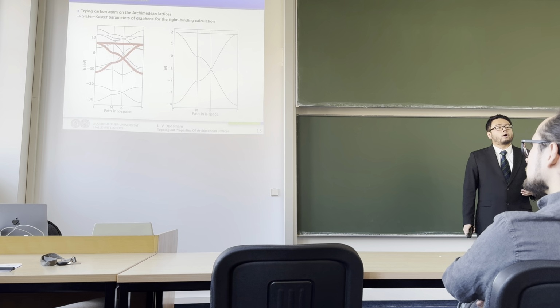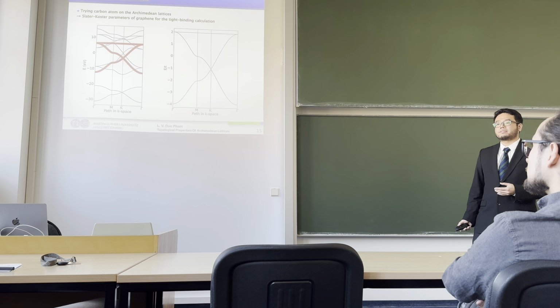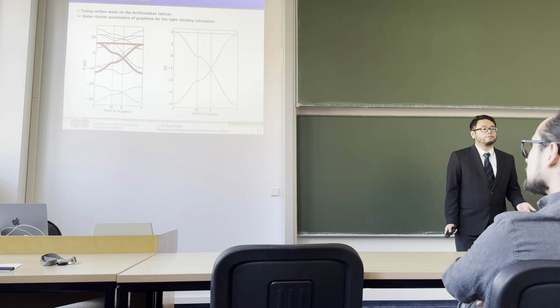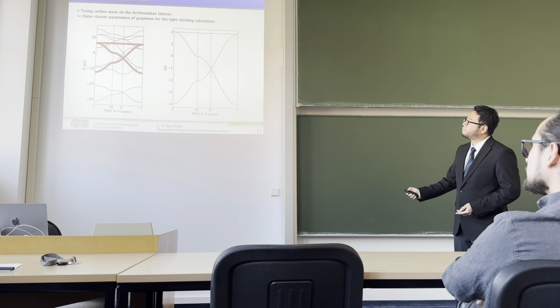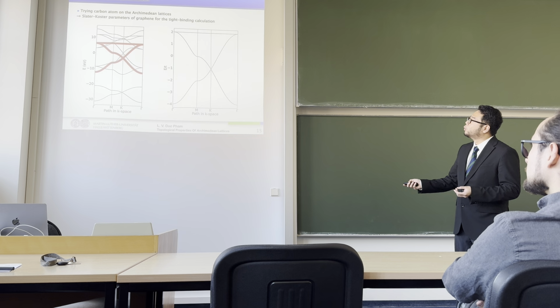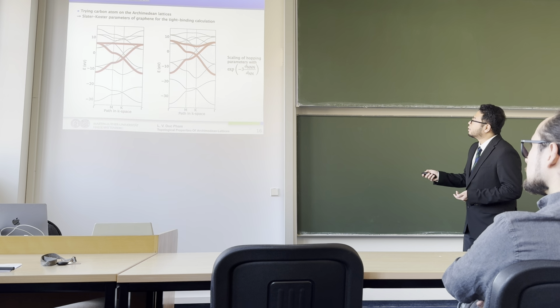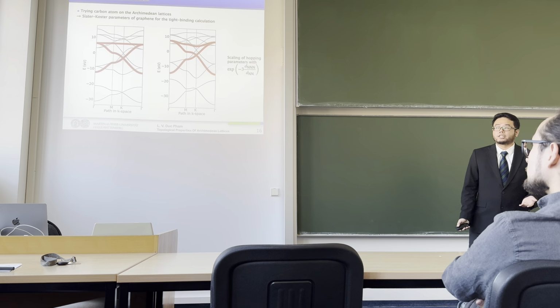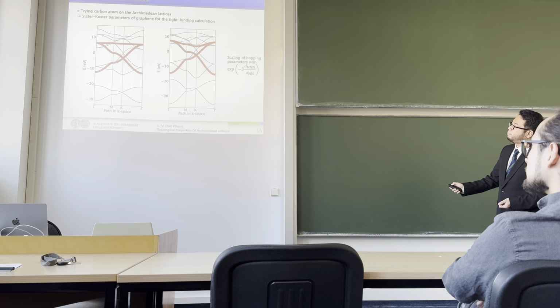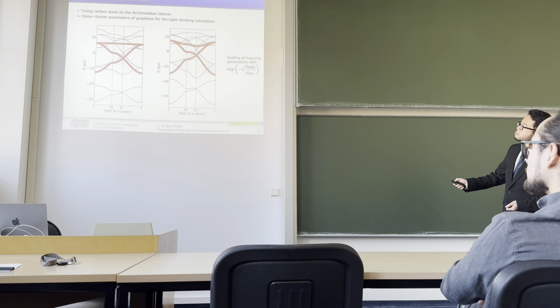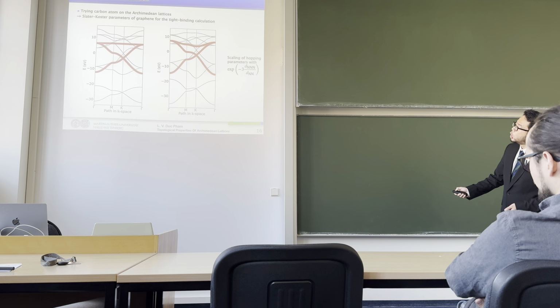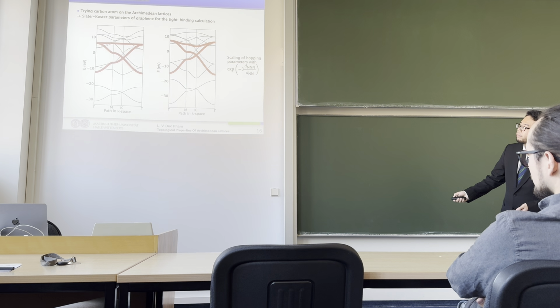And one of the reasons why the Kagome lattice is one of the favorite systems of physicists over the last few years is because of this flat band. But if you take the next nearest neighbor hopping into the calculation, then the flat band will gain dispersion. And you can also see that the next nearest neighbor hopping also changed the total bandwidth of the band structure.